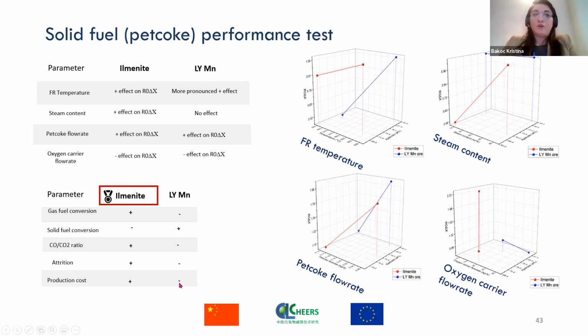So if we take into account all the most important parameters that we identified for the operation at different scales, but more importantly, that would be exploitable for the demonstration unit, we find that for the gas fuel conversion, ilmenite definitely shows better characteristics, while for solid fuel conversions, LYMN has achieved higher values of fuel conversion. Nevertheless, the CO to CO2 ratio was much closer to 0 in operation with ilmenite, which is a more satisfying result that we look for. The attrition affinity was definitely lower in the case of ilmenite, so we would say that the performance is better for ilmenite in this parameter as well.